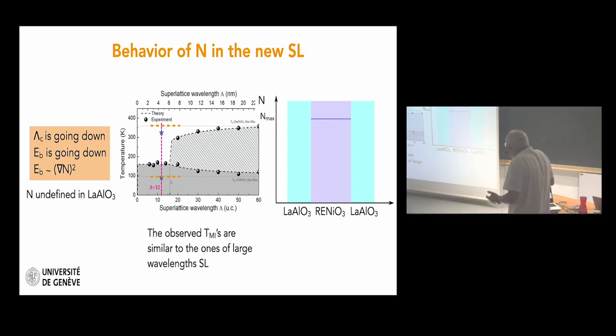So our picture is that probably our order parameter n, which is not defined in lanthanum aluminate, because lanthanum aluminate has no d band, is more or less constant. And there is no bending, and if there is no bending, there is no cost due to this phase boundary.